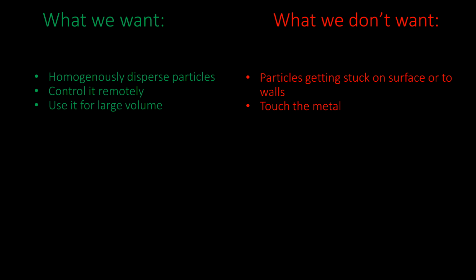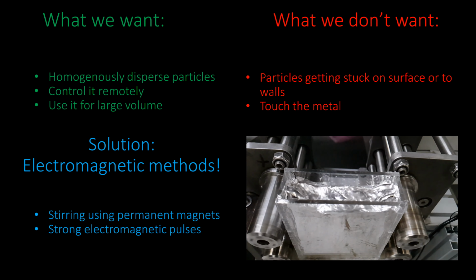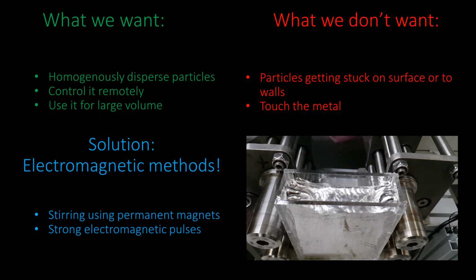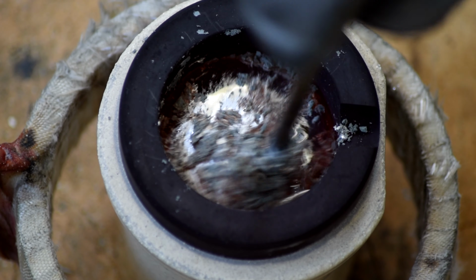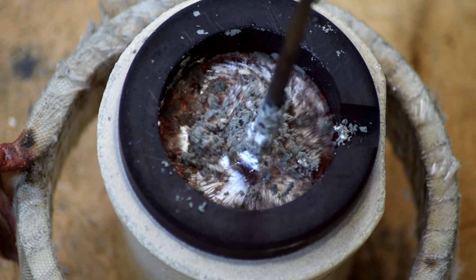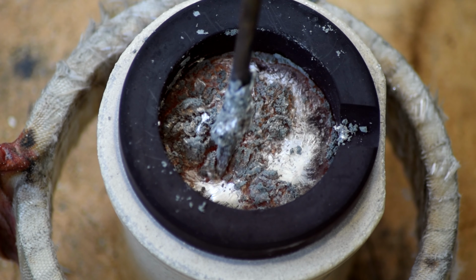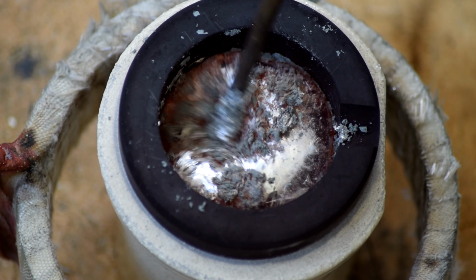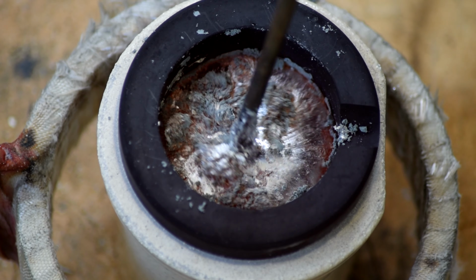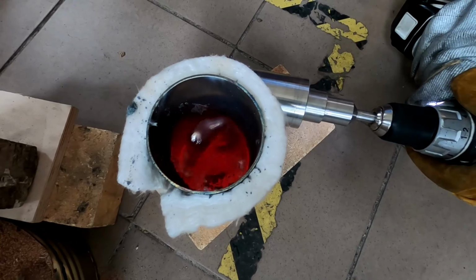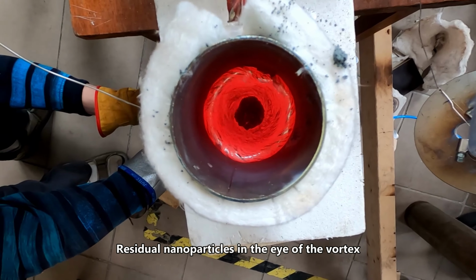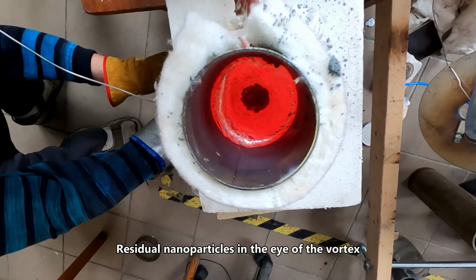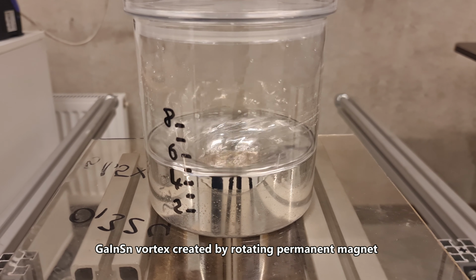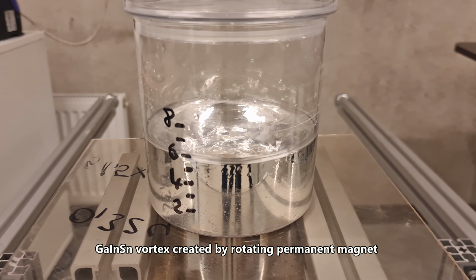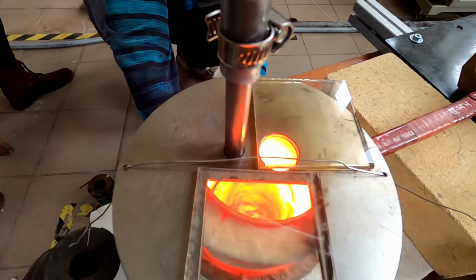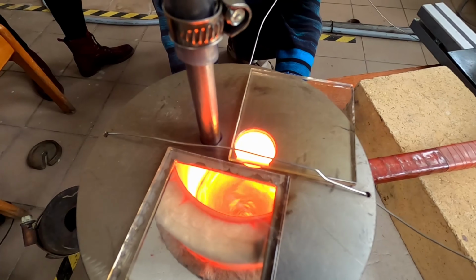We want a similar metallurgical method, but without direct contact with metal. An electromagnetic method. Mechanical stirring, like you would simply do with food, works for some particle and metal pairs. Unfortunately, due to density difference and surface tension, not for all pairs. So we have to get more creative. Our approach is to make a more intensive electromagnetically generated flow in molten aluminum, and then try particle in-mixing. We do that by using rotating permanent magnet technology, which can induce intensive flows in liquid metals.